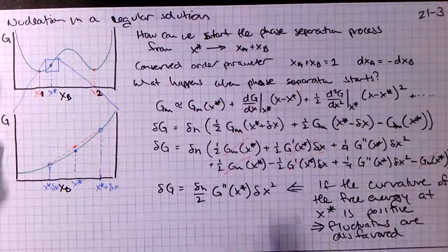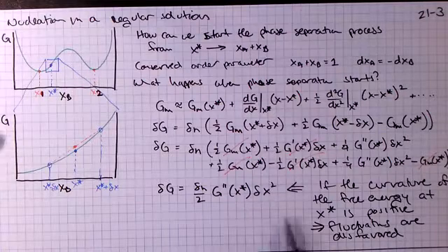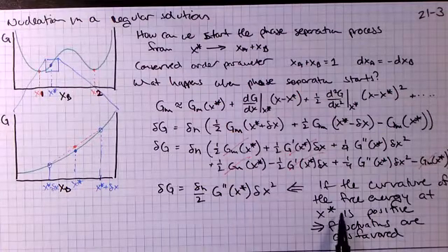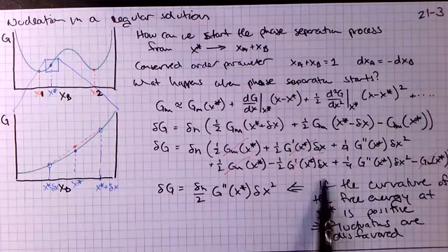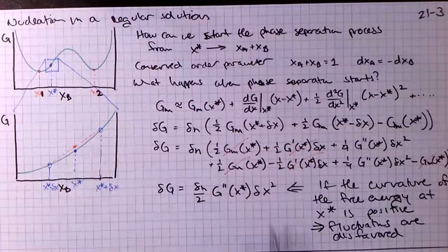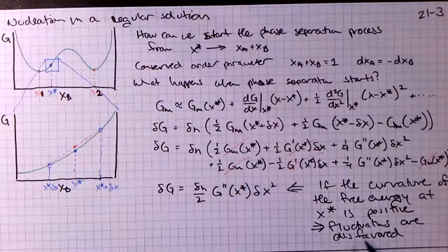And this is without putting in any surface energy. Even without any surface energy contribution, the fact that you have to phase separate locally and that's going to raise your free energy leads to a disfavoring of the fluctuation and therefore a barrier to nucleation.